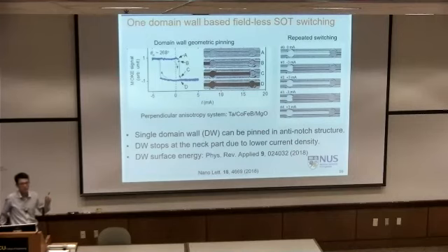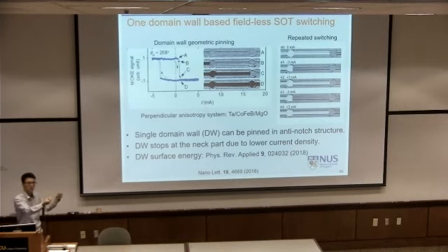Well, you can consider it as a conductivity concept. For example, as I defined, it is spin conductivity divided by charge conductivity. So when you look at a material system, I measure longitudinal or transverse conductivity. My conductivity in the transverse direction can be larger than in the longitudinal direction. Then why can't the value be more than 1? But if you define it as a current, that is the problem, because your current should be a conserved quantity. So you imagine, I injected 10 electrons, then you want to count how many in the lateral and the transverse direction. Then you have, I think, the problem.